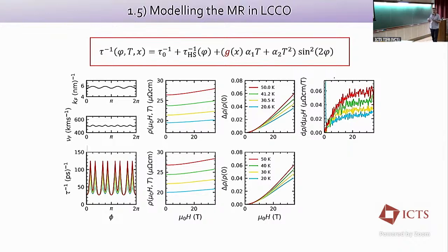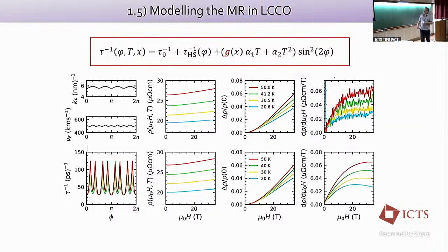We get the size of the magnetoresistance and then we get to a reasonably good accuracy the slope as well. But notice that there is some tendency to deviate from linearity at high fields and low temperatures here, because we've not made these hotspots extremely strong. They are broadened because we're outside of the antiferromagnetic ordered state, so you expect these hotspots to have some finite width.